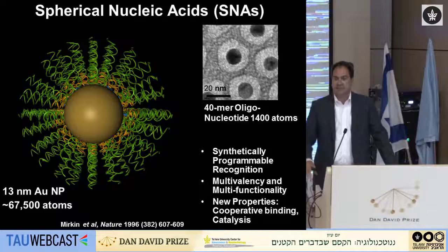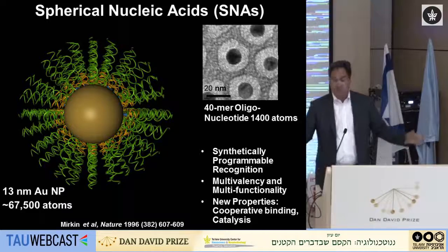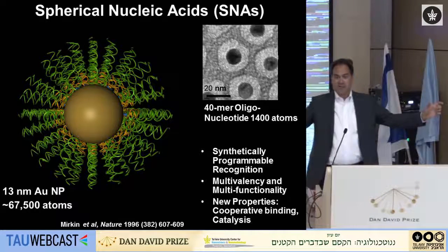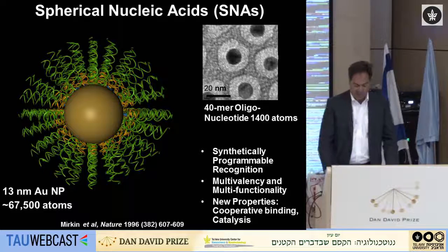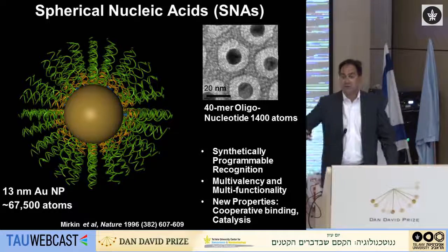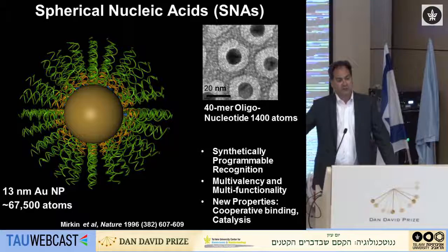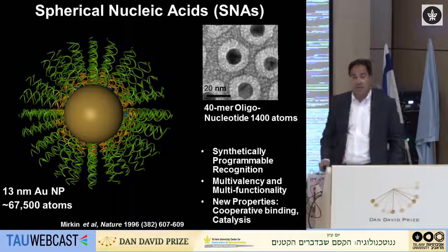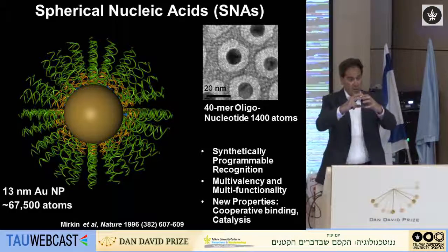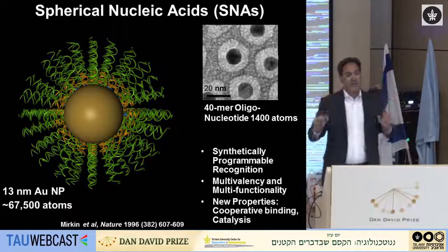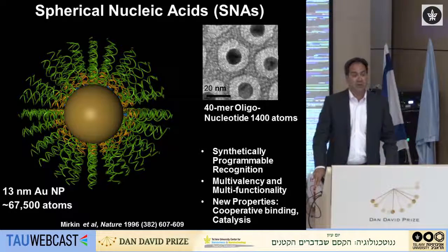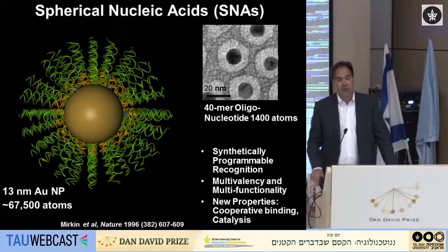And so that set us on an odyssey to begin to look at the properties of these structures, to look at how we could make different types of structures. And we discovered a lot of things along the way. One of the things we discovered was, first of all, when we make these architectures, it's not one strand of DNA per particle, it's many strands. And that's why I use the term spherical nucleic acid. Under the right conditions, you can create structures that in cartoon fashion look like this on the left. You can see the electron microscopy images on the upper right, where you have a particle core, in this case a gold particle, surrounded by a shell of DNA or RNA or any specialty nucleic acid that you'd like. And that's a highly programmable construct.